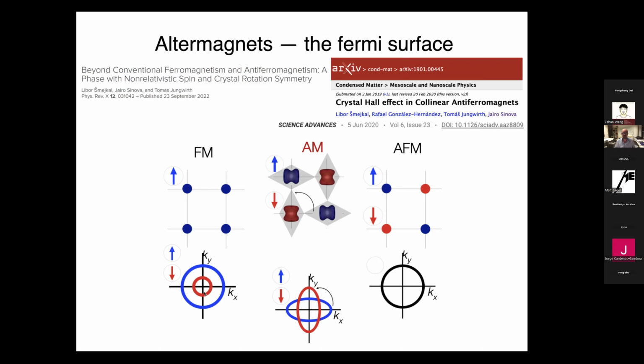If I have an antiferromagnet, then my Fermi surface is actually spin degenerate because all bands are spin degenerate at all momenta. But now if I have an altermagnet, where if I go from one sublattice to the other sublattice, I have not only to flip the spin, but also do a rotation of momenta or of the lattice. In that case, there is an up spin Fermi surface and a down spin Fermi surface that in general are non-degenerate. They are different and rotated and related to each other by a rotation. This is the case for a d-wave altermagnet. Then this rotation is actually 90 degrees. For g-wave altermagnets or for even higher order altermagnets, this rotation will be less than 90 degrees.